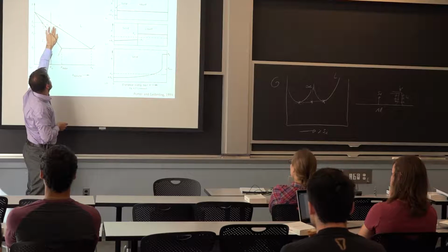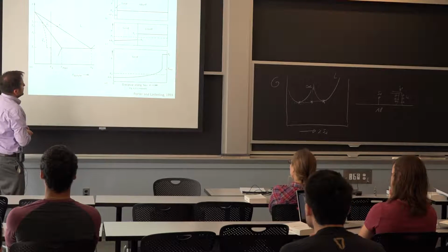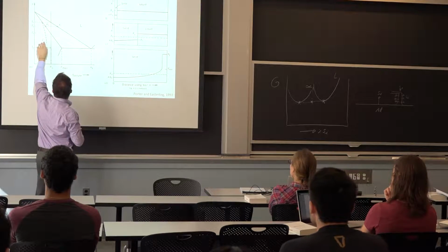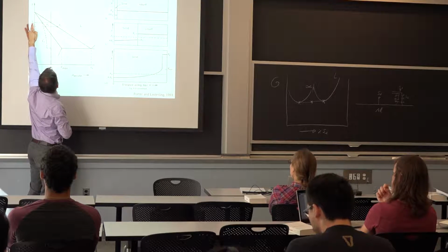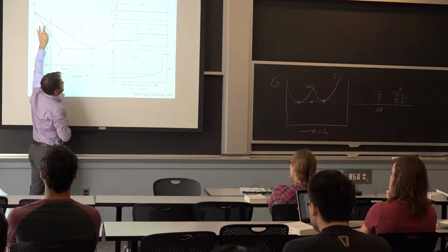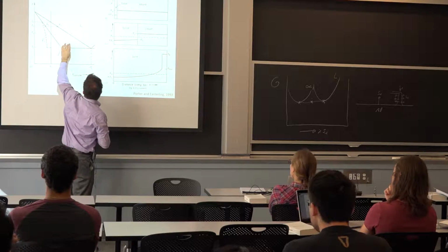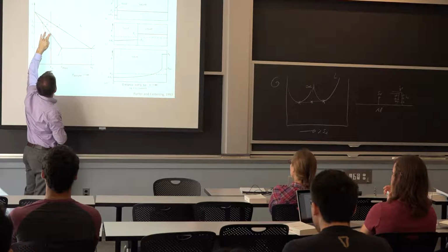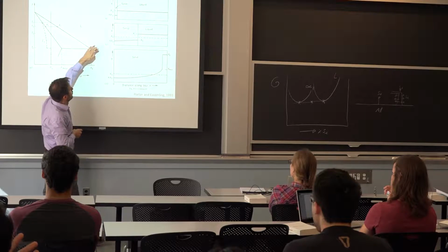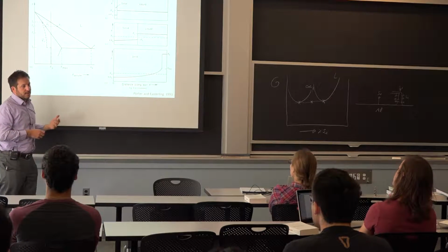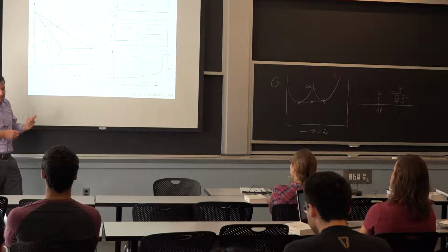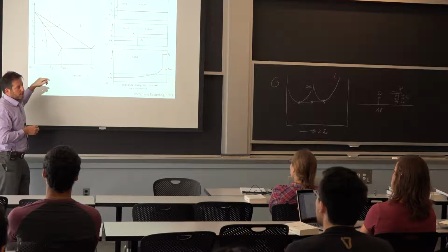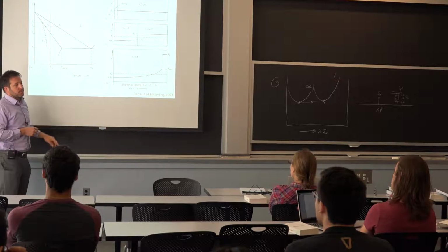So you respect this diagram, but the most common reality is when you start to form your solid, say at this temperature T1, you form it at a certain composition, so that's right over here. And as you're going down in temperature, you're supposed to keep increasing that concentration, but because you don't go back to where you started, because essentially there's not going to be enough diffusion in the solid, you end up with less on average of the alloying element in the solid as opposed to the liquid.